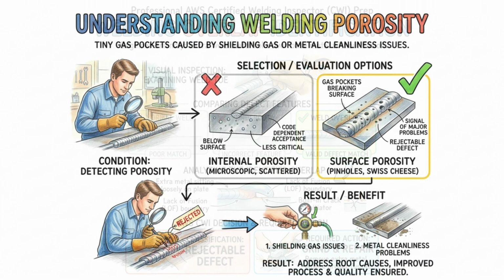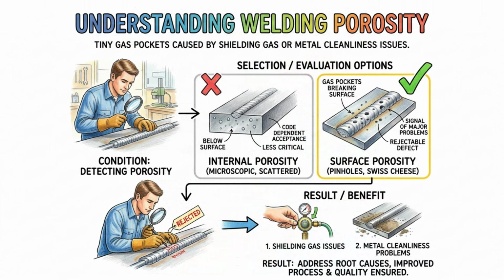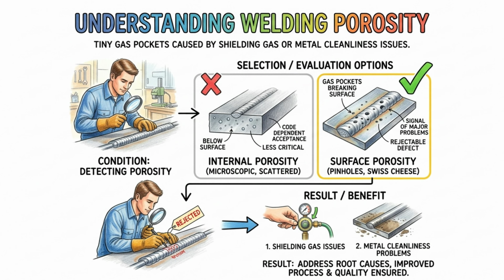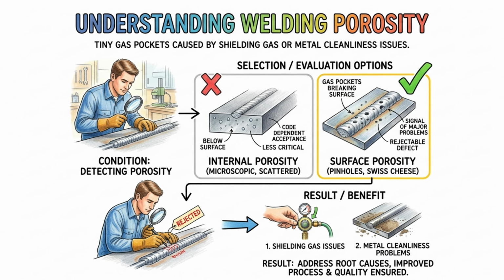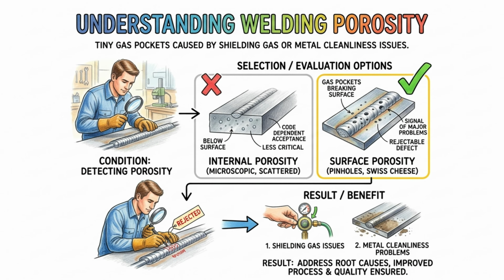Porosity is another major issue, appearing as tiny gas pockets trapped inside or on the surface of the weld bead. Often called pinholes, surface porosity looks like a Swiss cheese pattern of tiny round holes breaking through the top of the metal. While scattered, microscopic internal porosity is sometimes tolerated by codes. Any porosity that breaks the surface of a highly stressed weld is usually rejected. The presence of surface porosity is a clear sign to the inspector that something went wrong with the shielding gas or the cleanliness of the metal.